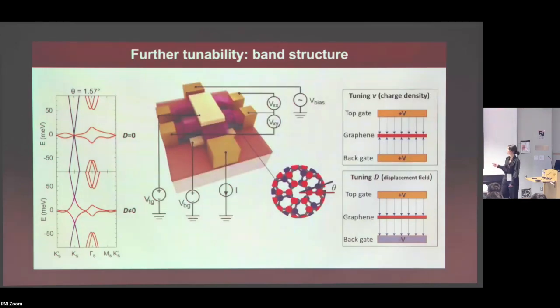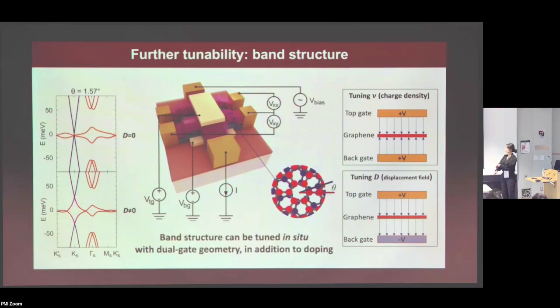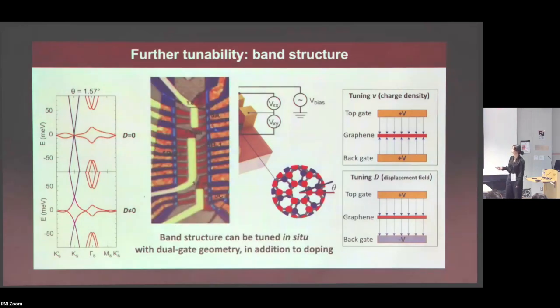And how do we do this? It's very similar to how we achieve doping, but this time we put two gates, one on the top and the other one on the bottom, and then you can independently control both the charge carrier density, the doping, and the displacement field by tuning the two different gates and some combination of them. So that's the device, and here's an example of a typical transport device that we make for this kind of sample.